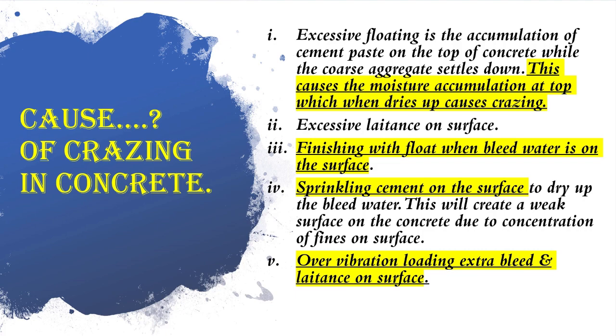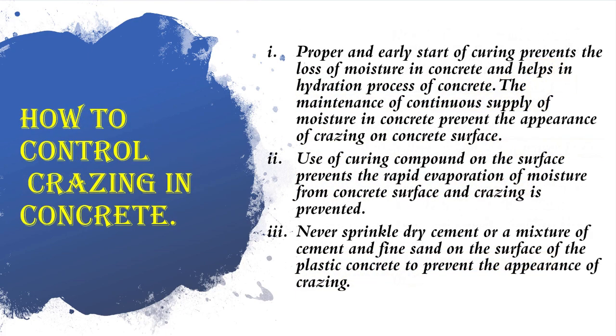How to control crazing in concrete: Proper and early start of curing prevents the loss of moisture in concrete and helps in the hydration process. Maintaining a continuous supply of moisture prevents the appearance of crazing on the concrete surface. Use of a curing compound on the surface prevents rapid evaporation of moisture and crazing. Never sprinkle dry cement or a mixture of cement and fine sand on the surface of plastic concrete to prevent the appearance of crazing.